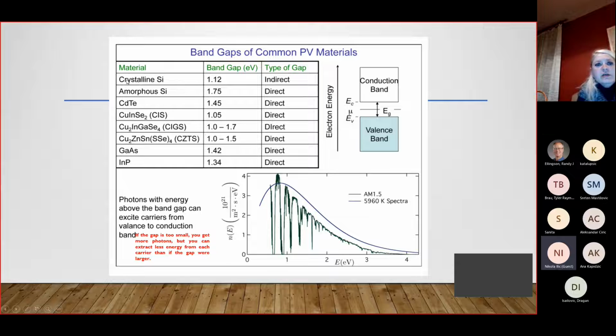And here you can see some of the most interesting materials, crystalline and amorphous semiconductors, and their band gaps. Crystalline and amorphous silicon is something like 95 to 97% of the market. Then there is also the quite widely applied thin film cadmium telluride with quite a good band gap, 1.45. Then copper indium selenides, then CIGS and also CZTS, which is a combination of copper, zinc, tin, and selenium. And then we also have gallium arsenide and indium phosphide.